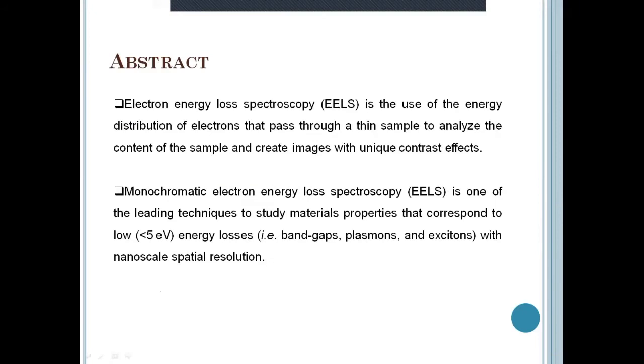To begin with the presentation, I would like to present the abstract. Electron energy loss spectroscopy is an analysis of the distribution of the electron energy emergent from a thin specimen due to its inelastic interaction. An EELS spectrum contains a great deal of information about the specific atoms — not only what they are chemically, but also their electronic structures, bonding states, nearest neighbor distributions, coordination numbers, dielectric constants, and band gaps.